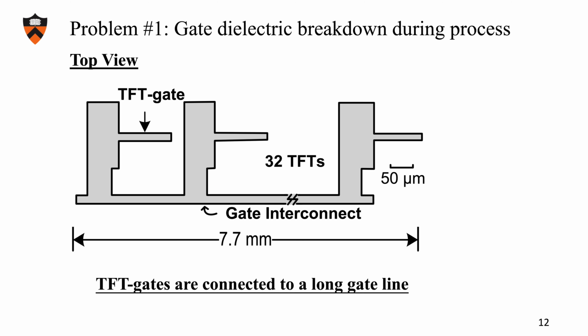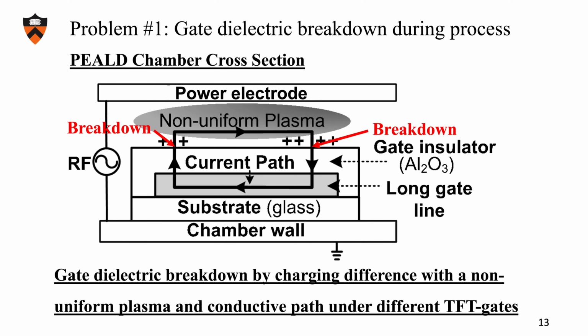Let's first look at the top view of part of a circuit. We can see that the gate metal of the transistors is connected to very long metal traces. In plasma processing, we look at these long metal traces. When they are loaded in a PEALD chamber, because of the non-uniform plasma we assume, the surface of the sample will be charged differently at different locations. The long gate lines basically serve as a current path. Plus, the substrate is isolated. There will be current tunneling through the depositing oxide, as shown in the figure. This tunneling will make the oxide break down.